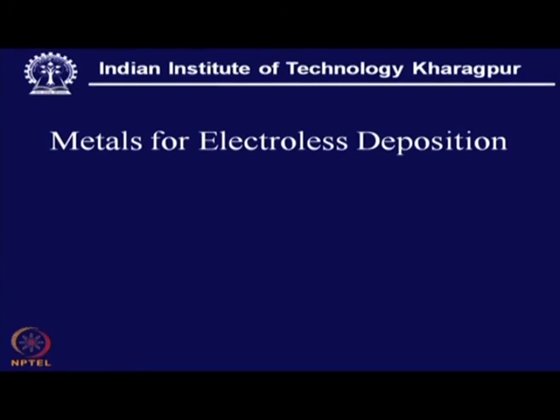Now, metals for electro-less deposition, we have all the metals, nickel, chromium, cobalt, we can have also silver, copper, gold, everything is possible. But what is advantageous, we find along with nickel, we have a little bit of phosphorus also coming from this hypophosphite, and that nickel phosphide, with a little percentage of phosphide, adds to the hardness.